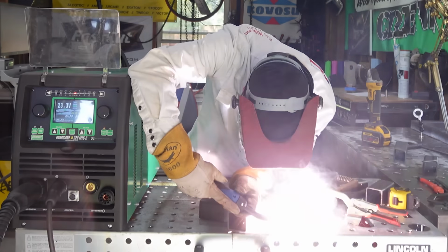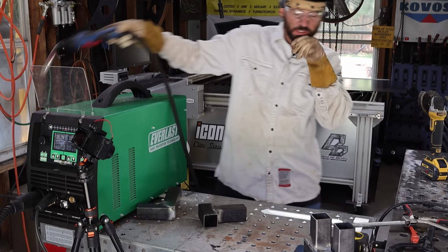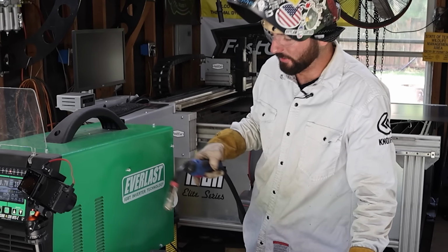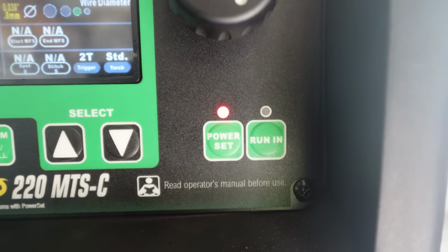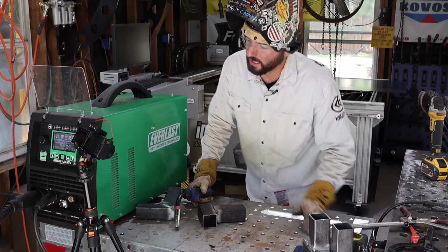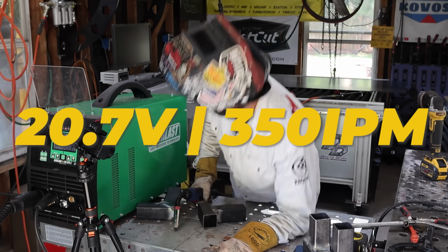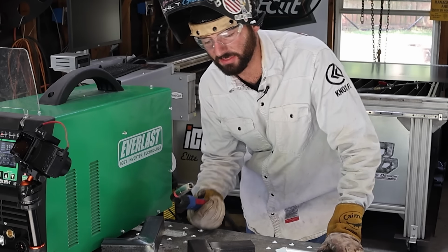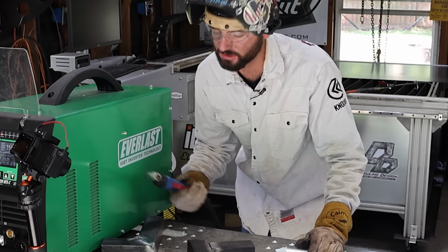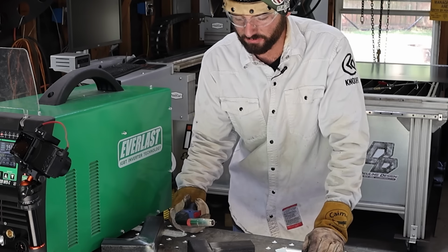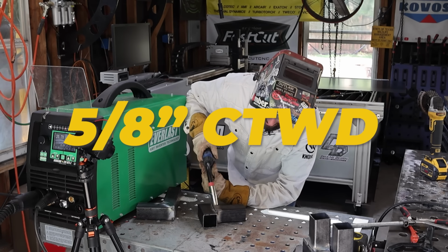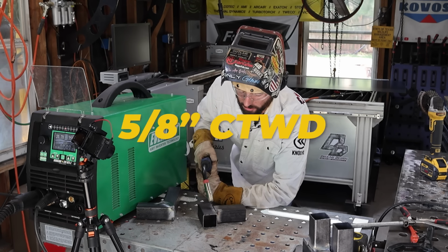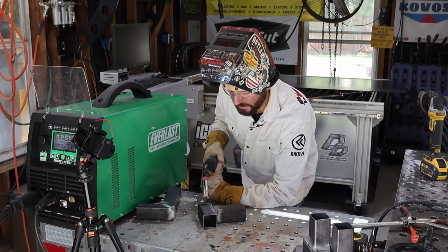Now that all of our weld joints are nice and tacked together, we tacked everything with the power set mode on this Everlast Hurricane, and it set everything to about 20.7 and 350 inches per minute. And again, we just set that to the wire diameter and the material thickness, and the machine gave us the settings. We're gonna maintain about 5/8, half an inch or so away from the material. We're gonna drag every weld.